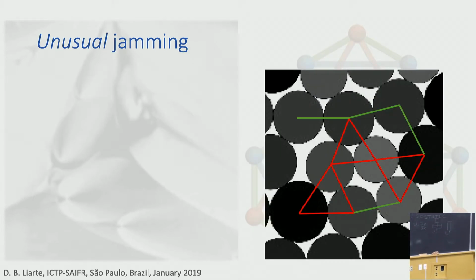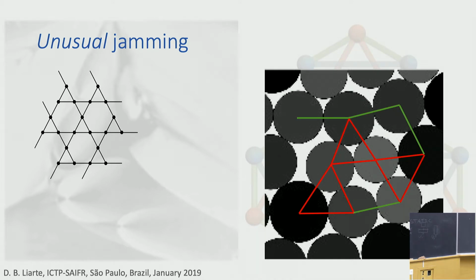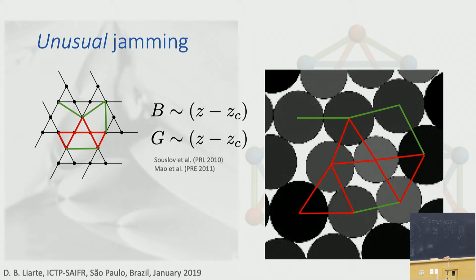But jamming is not only ubiquitous, it's also very unusual. And I'm showing again the network of contacts. There is a lattice that I remember when I look at this picture with these triangles. You can think of something that looks like a Kagome lattice that I'm showing here. It also has triangles here and there. And I'm even going to cheat a little bit and draw some red lines that look pretty much like this cluster, and some green lines connecting next nearest neighbors, just to show that you can get something with a topology that looks pretty much like a jammed lattice.